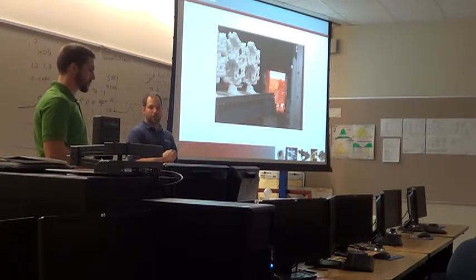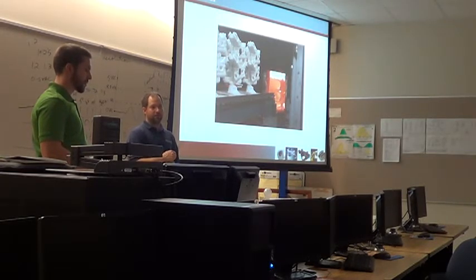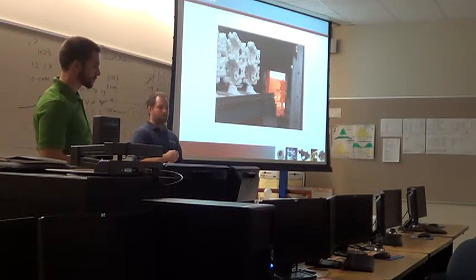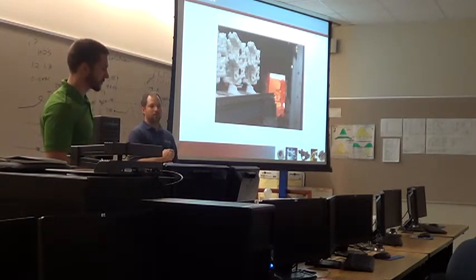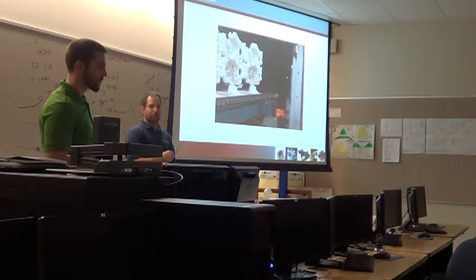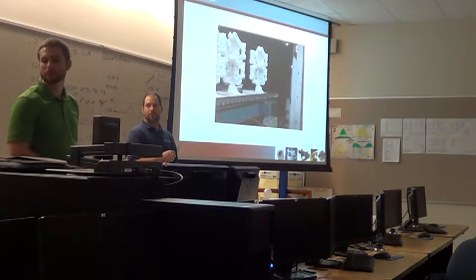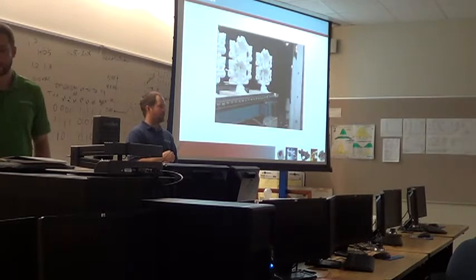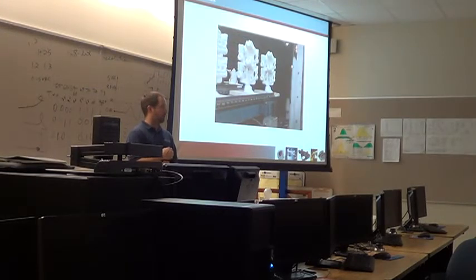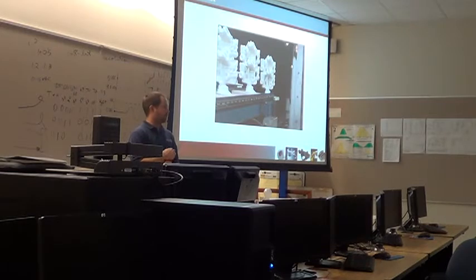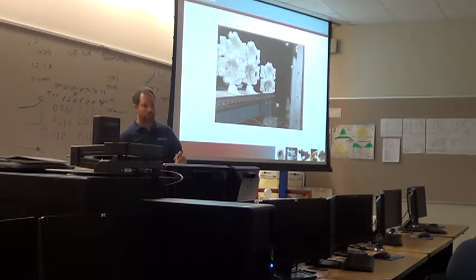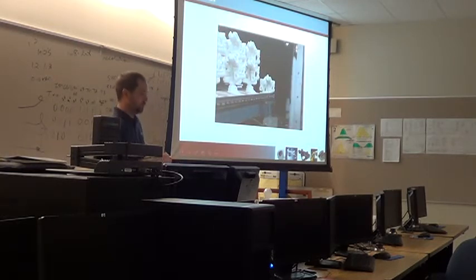We then run it into a burnout oven. The burnout oven is 1800 degrees. We burn out our molds for about 4 hours. And what that does is burn out any residual wax that's left in the shell, and it sinters the ceramics to make it strong. So we use a pusher type system burnout oven, so when we pull one mold out of the front to pour it, another one gets pushed in from the back, and it's like a conveyor line that goes all the way through.